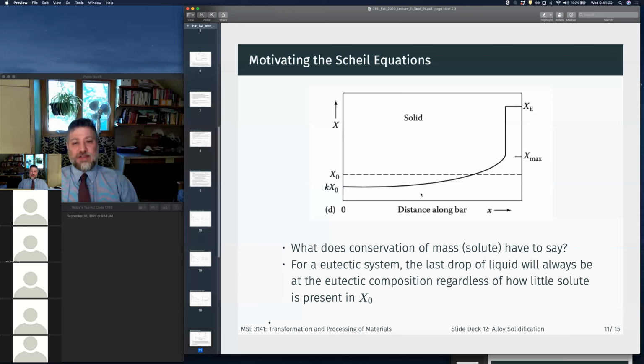So that means if we have a directionally solidified, right? So even if we don't have a directionally solidified material, what this means is that after we do casting, if we want the part that we cast to have a uniform composition and uniform properties, we need to do a diffusional heat treatment. We're going to need to hold this at some temperature below the eutectic point, the eutectic temperature, right?